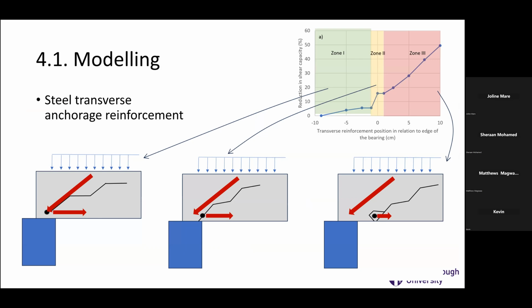And we modeled this situation of the bar. So you'll see there, we've got the bearing support in blue, and we've got a plank over it with a UDL on. And we modeled this, and we moved that critical bar left and right. And you'll see the results at the top left. So if your bar is over the support, you've got enough shear capacity for the plank. The more it moves over the edge of the bearing, you get a reduction in shear capacity. It's not a binary yes, no. It doesn't go from being fine, you move it 1 millimeter and it's not fine. You get a reduction in shear capacity.